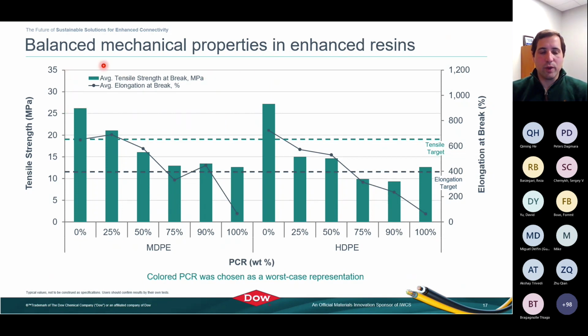Again, you can really reach a nice balance of properties with the enhanced resins. Here again, it depends on how much you'd be wanting to target to claim recycled content in a cable. But also looking here again at a worst case scenario, it looks like we would say right about 25 again to upwards of 50 based on optimization. So there is opportunity to fall into this range based on type of polymer and type of PCR used. But it just gives you a flavor for how the materials will perform at varying levels of recycled content.